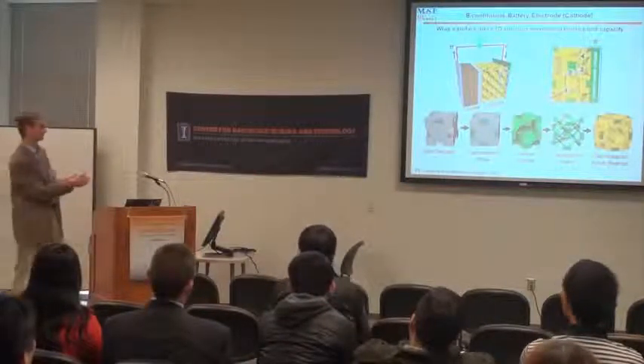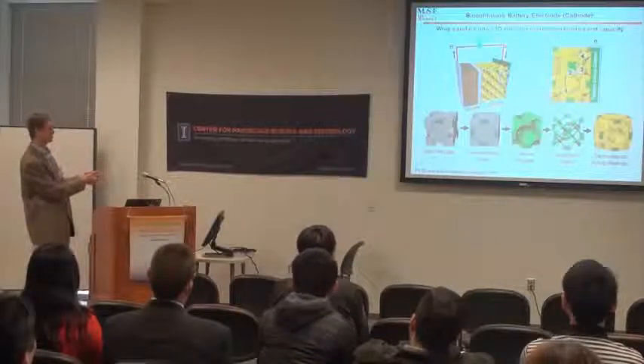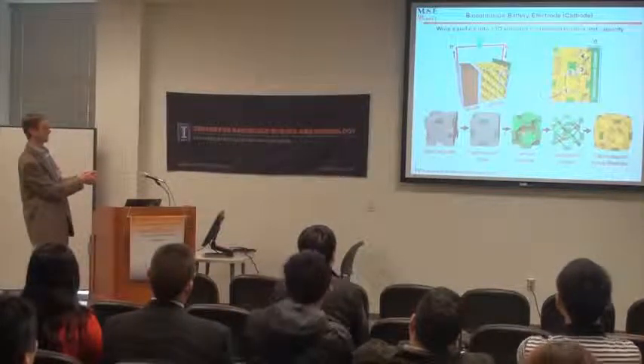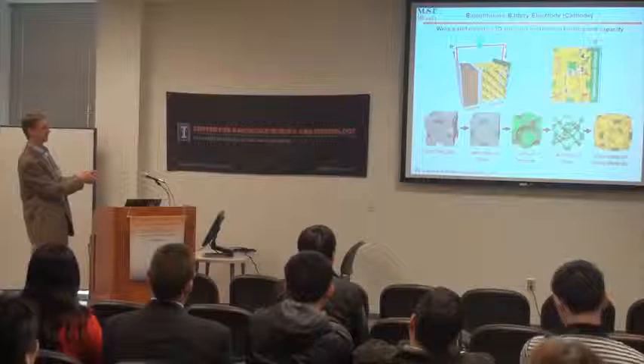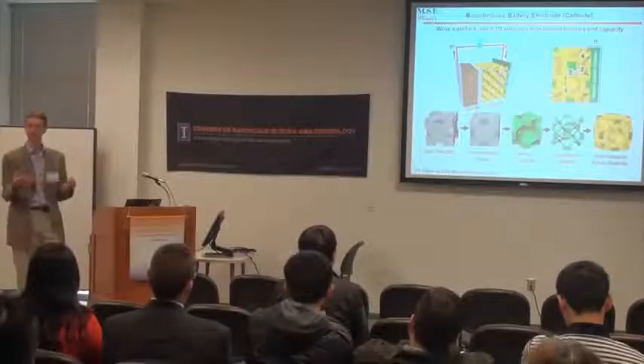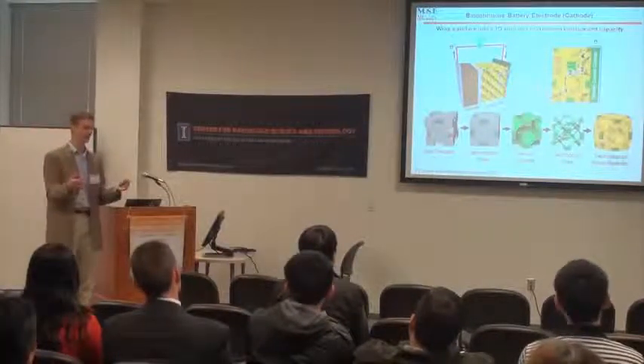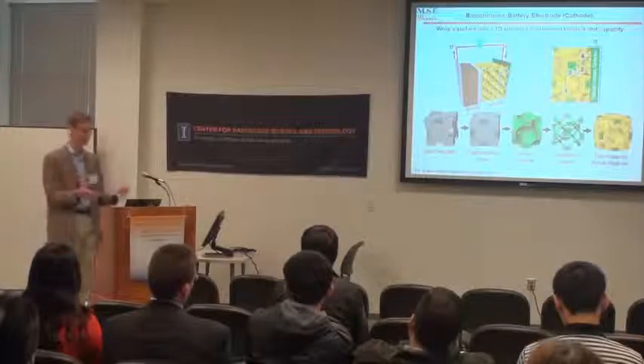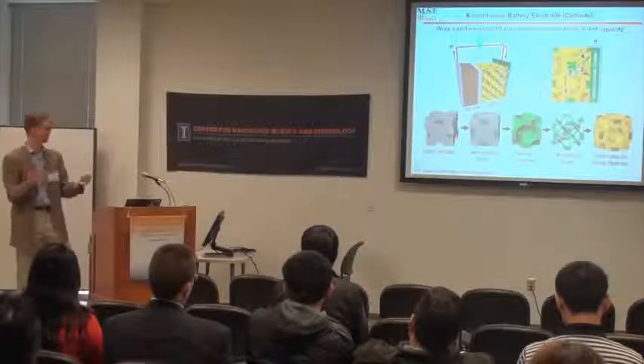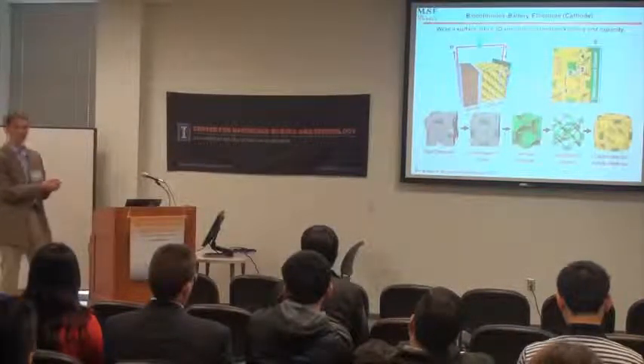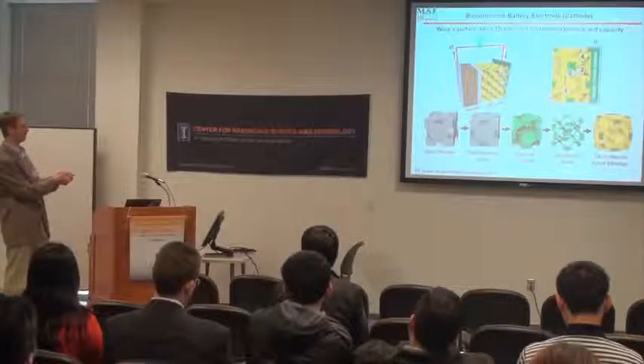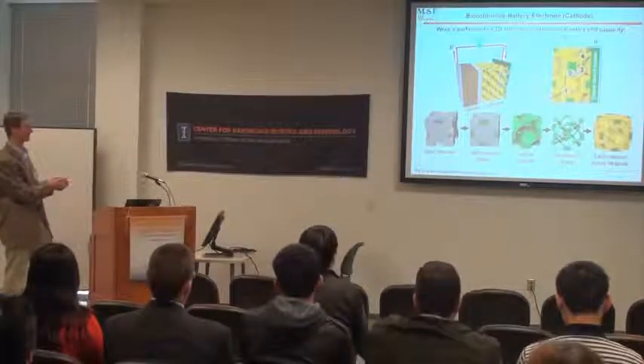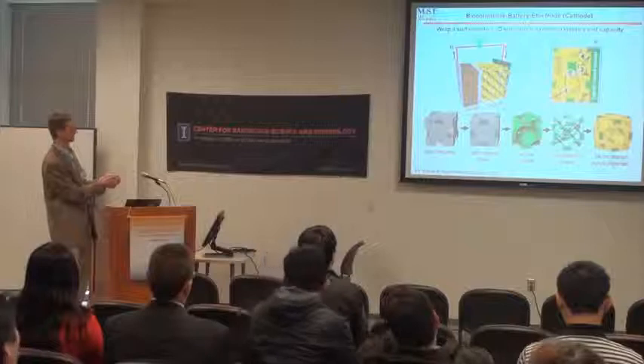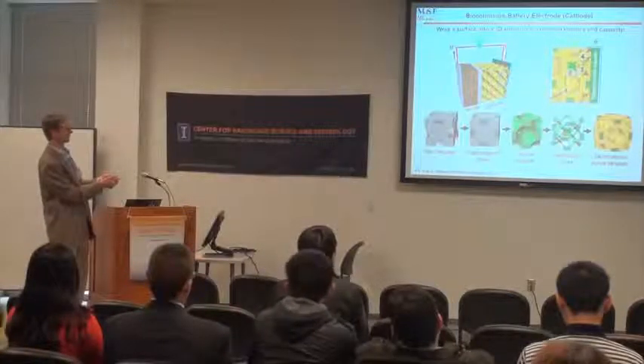And so what we realized was that we could take our metal structure here, electropolish that structure, and open up, creating a structure which was about 90% open voids. So I also learned a little bit about scanning probe in the course, and perhaps that's turned out not to be as useful for my individual research career, but you know, it's one of those things. It's not what you expect to learn, it's the thing you didn't expect to learn that really mattered.